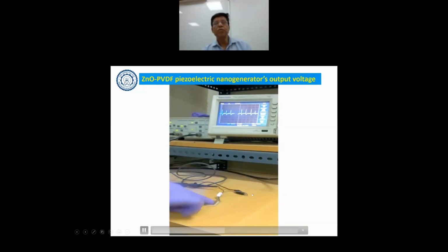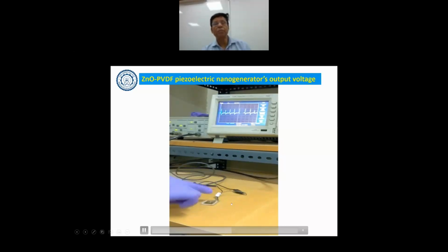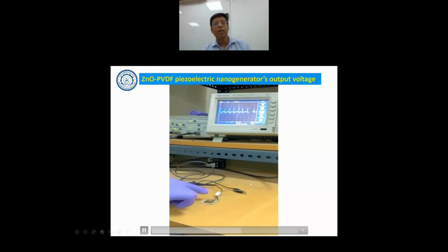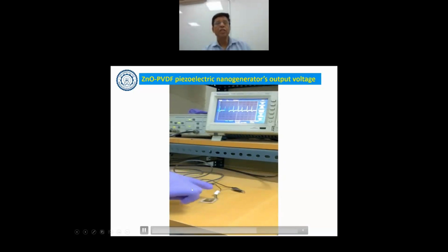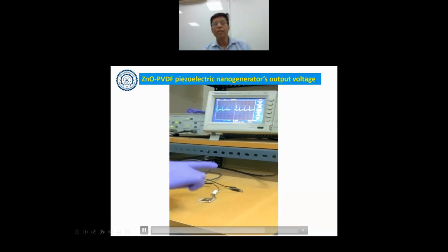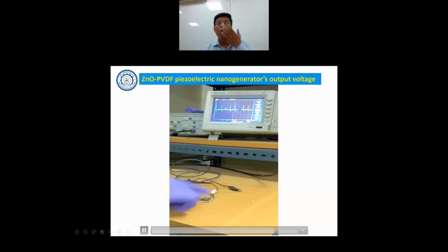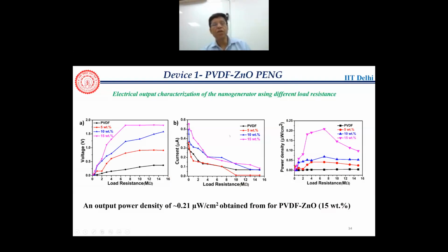And there's another measurement we did, the KPFM measurement, again using our atomic force workstation, to find out the surface charges on this film. And these are very interesting things because you can find out the work function of this film. Once we have this zinc oxide PVDF film, its work function gets changed from 4.83 to 4.57.